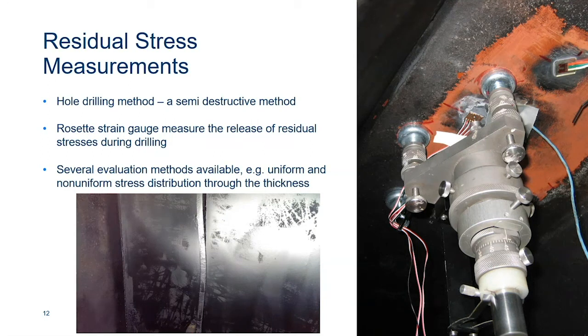The people responsible for the bridge were worried if these residual stresses were too high and if they had to do something about it. So I was involved in this measurement campaign where we measured the residual stresses on the bridge deck. As you can see in the photo on the right, it was done with the hole drilling method, where we bore a little hole in the center of a rosette strain gauge, which measures the release of the stresses when you make this little hole.